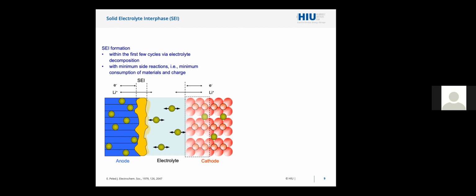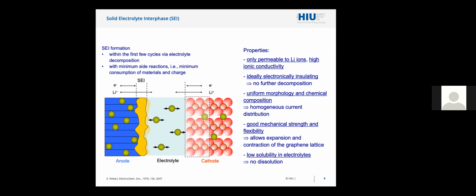One is the best. And it should also occur with the minimum amount of side reactions, because obviously side reactions lead to the consumption of the lithium, but also of the charge stored. Never forget that the amount of charge stored in a lithium-ion cell depends on the amount of lithium stored in the cathode. So the more lithium and charge is consumed for the SEI formation, the less will be the capacity of the cell at the end. What are the properties? What we hope we get out of the SEI.